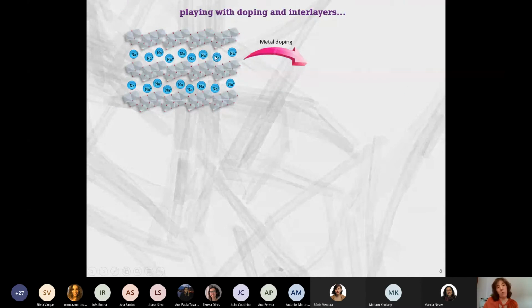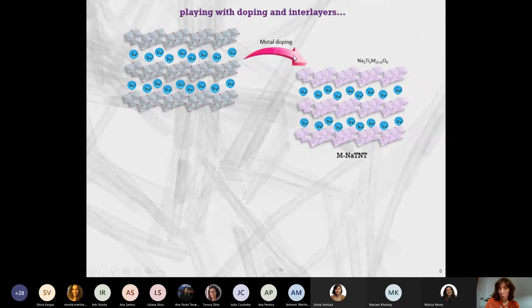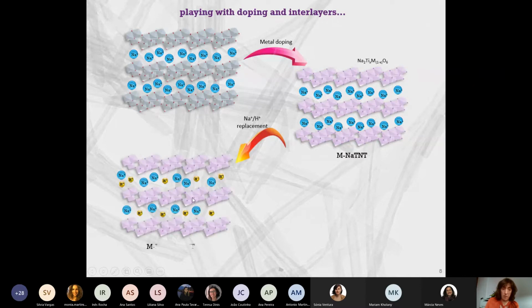But one thing is to replace the sodium, but we can also think about doping this material. How? Well, we want to replace some of the titanium that is here in the octahedra by a metal. And then, if we have this new material with titanium and metal here, of course, the sodium is exactly in the same place, but we can also think of replacing this sodium by the proton, as I told you before, and we will have a material with proton and with dopant.